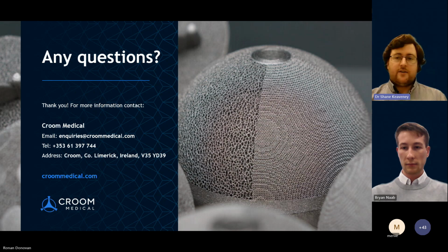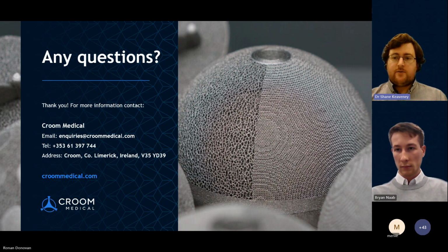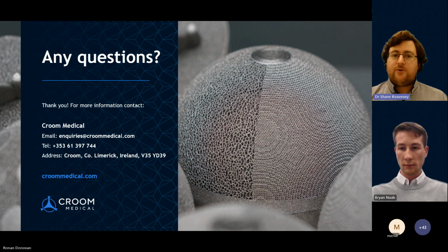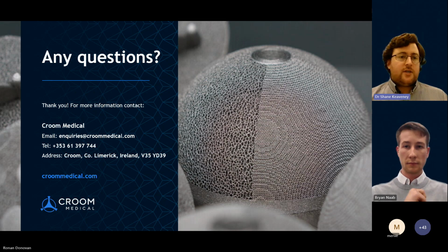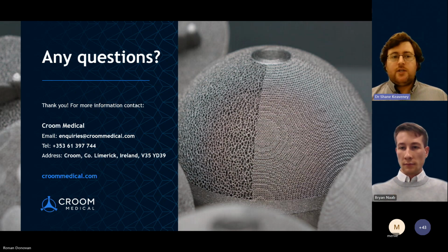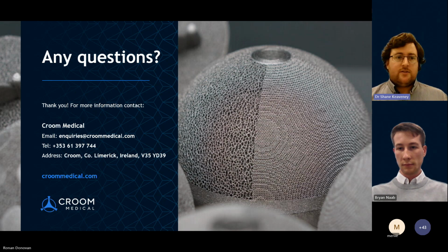And I see another part of Hannah's question is about the interface between lattice structures and solid structures. Just on that one, obviously the heat treatment is very important. But going back to Bryan's original point about how we evaluate these structures, the type of test method we use for those is quite important. Where we're looking at solid and lattice hybrid structures, that interface is obviously not polished. It's a printed surface, but we can do tests such as shear testing, fatigue shear testing, and tensile bond strength testing as well. That's something we can do within our lab, and we've looked at previously.